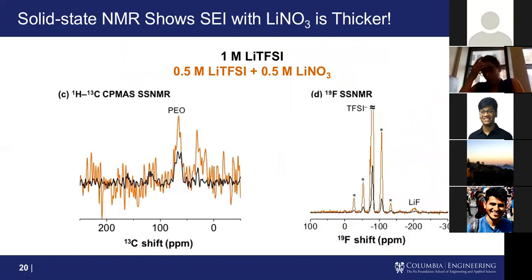So what's actually deposited? That's what's happening in solution. What's actually deposited on the surface of these lithium metal anodes? If we take a look at the carbon-containing species, we see something that's really interesting. We actually see that we have more of these polyethylene oxide type polymers when we have the nitrate present, and we see more lithium fluoride when we have the nitrate present.